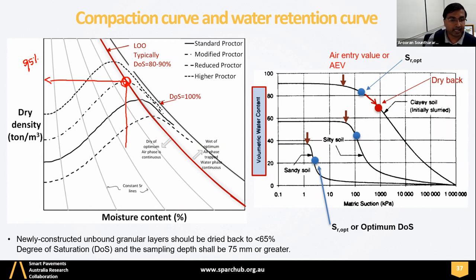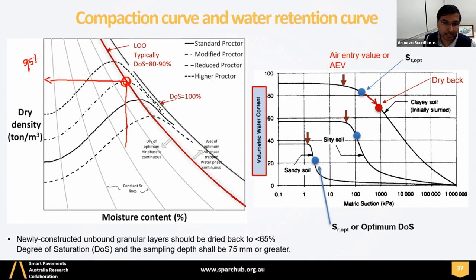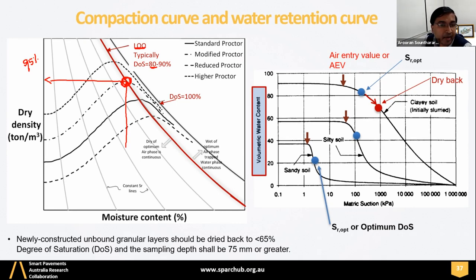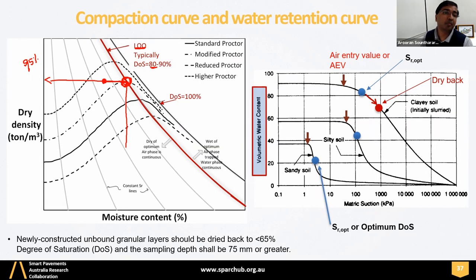And then after the compaction, newly constructed unbound layers should be dried back to a certain degree of saturation, normally 65, before the sealing is placed. So why is the pavement dried back, right? The reason is, normally the degree of saturation at the line of optimum is 80% to 90%, depending on the material type. And then when you dry back, the degree of saturation changes this side, right? So there are two main reasons why pavements are dried back in the field before we place a seal, or before it can be trafficked, right? This is a dryback process, and you will end up with some degree of saturation value here. So why have they been practicing that?